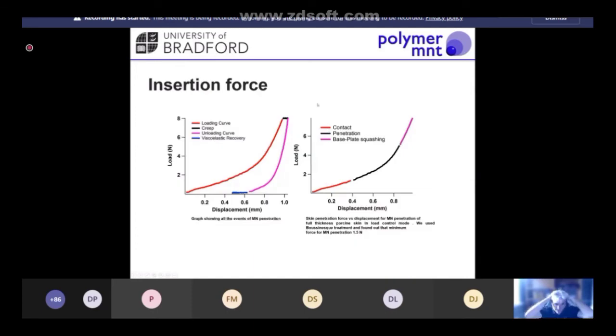So from doing that, we can measure the insertion force required for each needle in the array by doing single needle tests, or the array as a whole, to make sure the total force required isn't going to be higher than what is capable of being applied with a given applicator system. So we do lots of work on quantifying insertion force required. And this is particularly important for the larger arrays where you're trying to give quite a high dosage of drug in a given application.